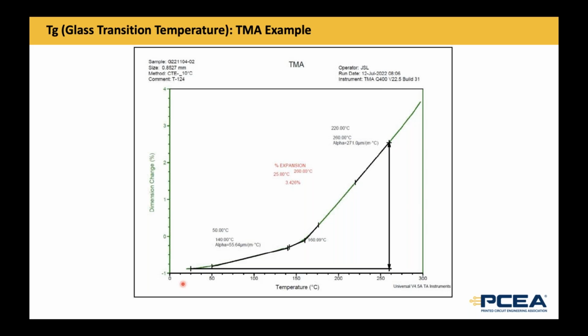XY CTE is a figure of merit and is measured. It is sometimes measured by TMA. It can be measured by TMA. It is also measured by other methods using a different setup so that you can get a more accurate XY. The Z-axis expansion is important for a lot of reasons, which Erica will cover. The XY expansion is important for other reasons and is a much lower number, in the 10 to 15 parts per million range for most materials, and is highly affected by the construction of the sample because the glass has a very low expansion and the resin has much higher expansion.